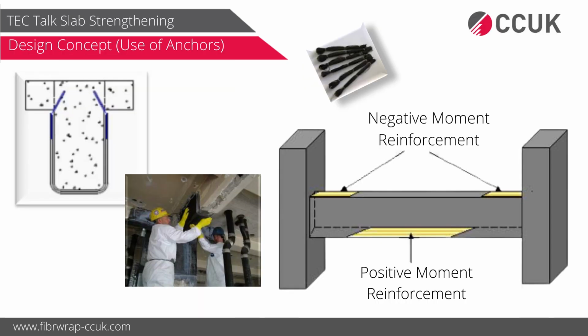So if we try to understand it in a very simple schematic, how the carbon fibre strengthening works, or what's the concept behind strengthening using carbon fibre, then this is a very simple schematic diagram which shows how the carbon fibre is applied and its purpose. One thing to note here is that carbon fibre has very good properties in tension, and it is always recommended to be applied onto the tensile face of the element. For that reason, it is applied at the underside and the mid-span, as we can see in the image.